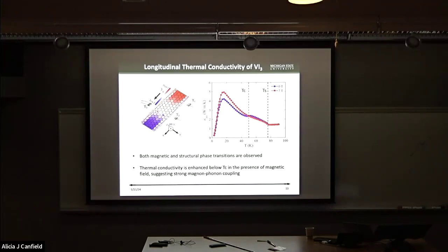A related question: at high temperatures, kappa is also still rising. What happens at high temperature? Unfortunately, here we used a sensor that did not go above 100 Kelvin. For this particular data, we only went up to maybe 80 or 90 Kelvin. But I would expect that it should go down at higher temperature.